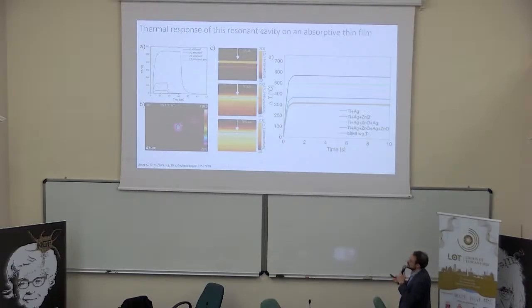So the effect is incredible. You can reach 550 degrees in a fraction of a minute; of course, it's 10 seconds to reach the plateau using the maximum of this power. This is the simulation, of course, that is completely flat. Here it's flat, and the rise is immediate, but it's a simulation. It makes sense for that.